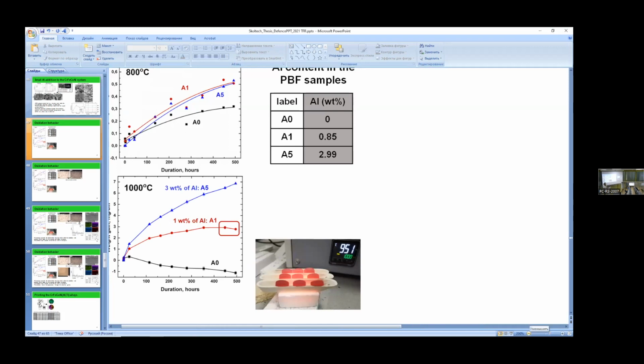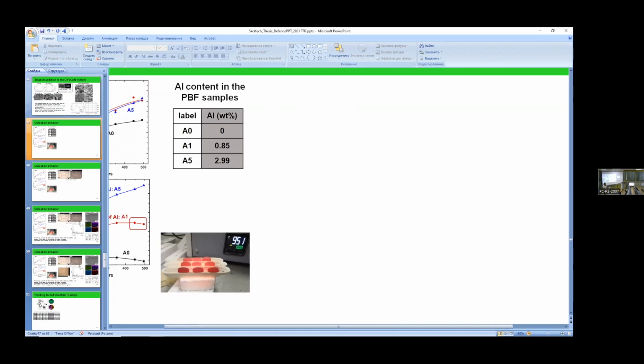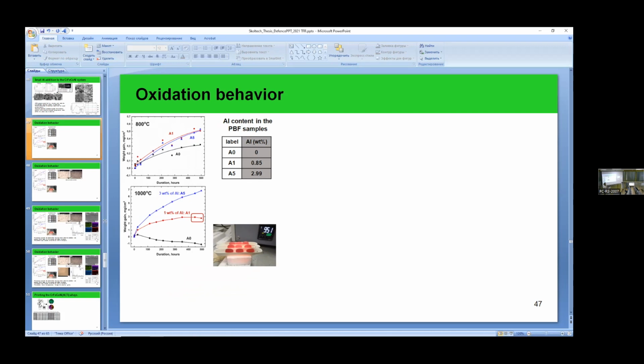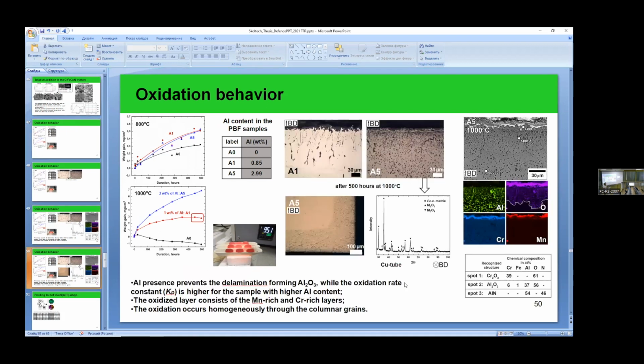But what happens at 1000 that delamination occurs? Because I guess the products of oxidation are similar at 800 and 1000, right? Yes, but the oxidation process goes more intensive, so it's more visible just in case of 1000 degrees Celsius, where we see the formation of this chromium and manganese oxide, and the last one is typically delaminated from the material. So we need to prevent the further formation of this material. Okay, so like, there is some misfit that grows, right? The misfit of the oxide layer and the specimen is increasing at 1000 degrees Celsius. Yes, which is causing this delamination. Okay, I get that.